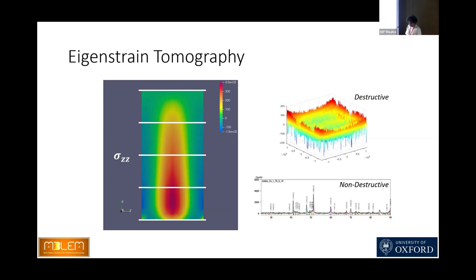With destructive techniques, we measure elastic response corresponding to stress relaxation caused by a mechanical process. For example, it can be cut into material and you can track the strains. This elastic response leads us to calculate eigenstrain distribution, or we can measure diffraction patterns for strain tomography.